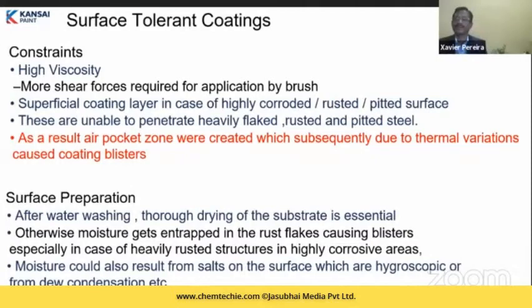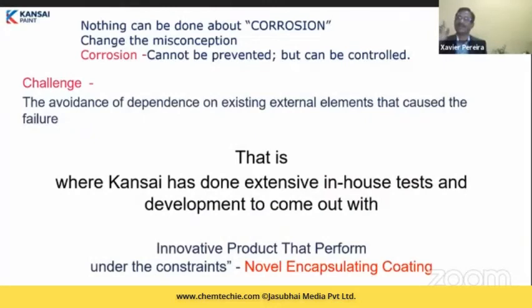What could be done was a challenge that we, at Kansai Nerolac, took up. And one thing which I always say is that many people say nothing can be done about corrosion, but I say that corrosion cannot be prevented, but it can be controlled, right? And the challenge to us was to avoid the dependence on these external elements, as I mentioned, the rough surface and the moisture. And that is where Kansai did extensive in-house tests to come out with a new development, okay, a product that performs under the constraints that I mentioned, and that was the novel encapsulating coating primer.